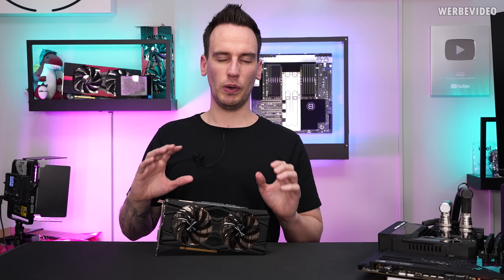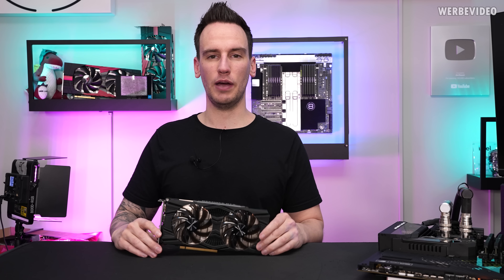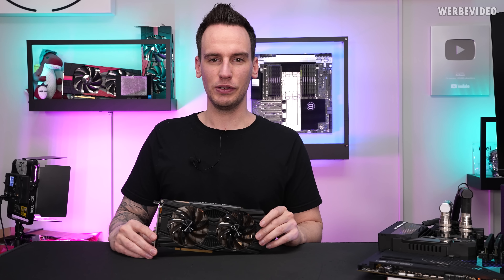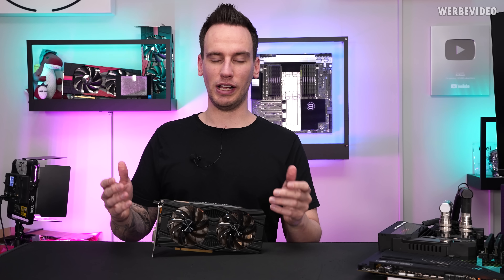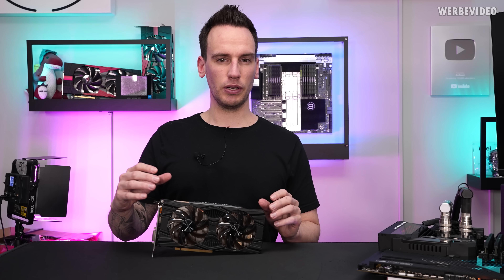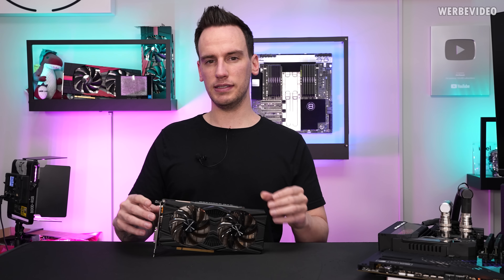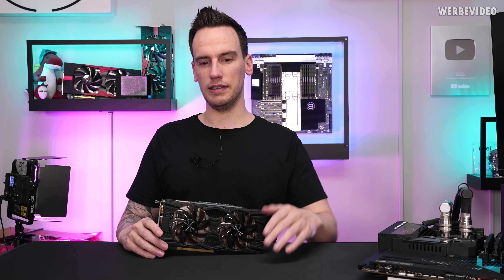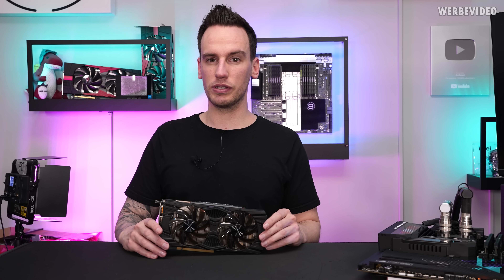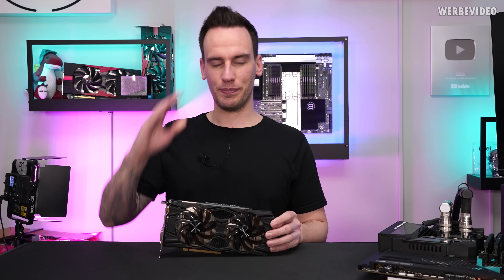The 2060 passed one hour of testing — temperatures didn't change at all, so I would consider this card fixed. Looks good to me, I will send it back to Michael, and I hope he will be happy about his card. I also hope it was interesting for you to see what kind of damage gallium can do to aluminium and also if there is a way to fix it. I also think that because the cooler was nickel plated, that actually helped to minimize the damage on the aluminium — because if there is no coating and the gallium can have direct contact to the aluminium, usually it looks much worse than this. Thanks for tuning in, see you next time, bye bye.